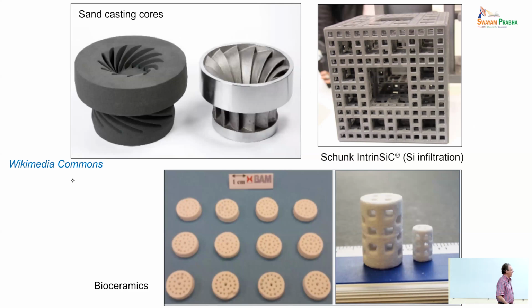I mentioned that you have residual porosity. One possibility is to fill the residual porosity using molten silicon, typically combined with pre-infiltration with a carbon source. In this way, you can make siliconized silicon carbide, which is one of the good materials for a lot of high temperature applications. Or you can exploit the residual porosity within the solid. For instance, when you're making bioceramic parts, then having porosity within the solid helps with the connection with the tissues and vascularization and other transport of fluids within the solid. So for certain applications, binder jetting is good.